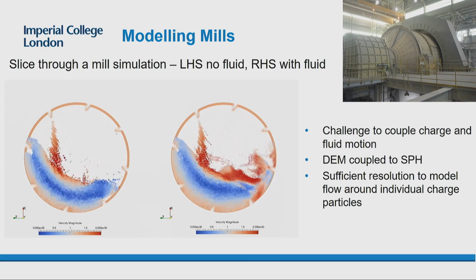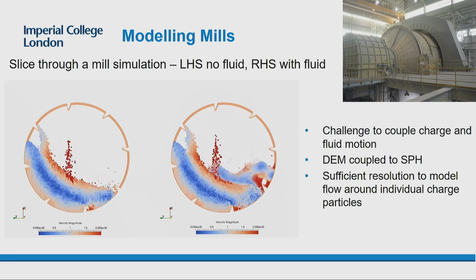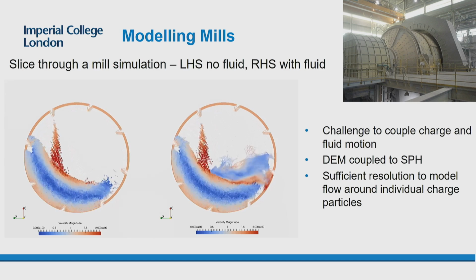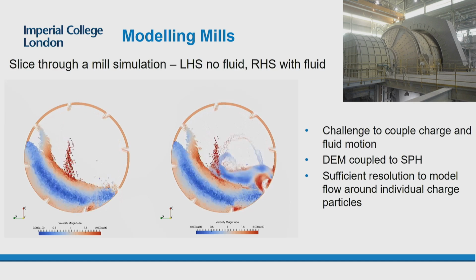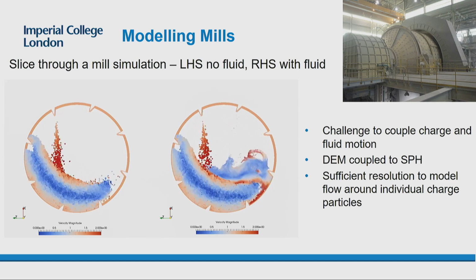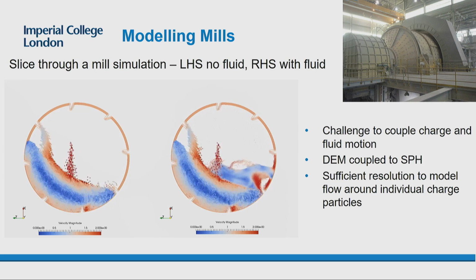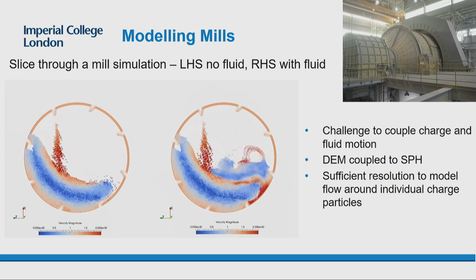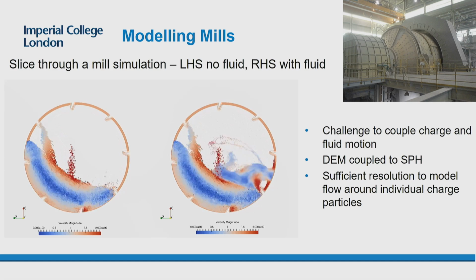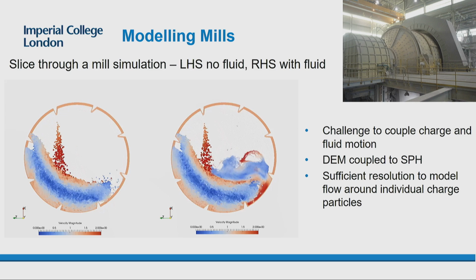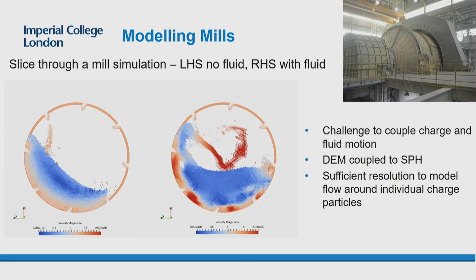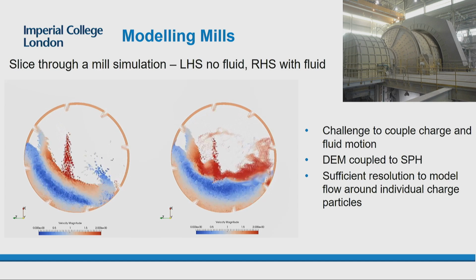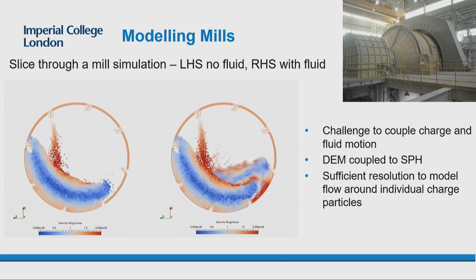So we've been doing a bit of work on the milling side, which is very much a new area. Again using that same SPH code, but this time coupled to another method called the discrete element method, we can start to simulate what's happening in mills. Here we have about 100,000 steel balls we're simulating, the things that are tumbling, on the left-hand side without any fluid, and on the right-hand side with fluid. The left-hand side is the sort of simulation routinely done by lots of different groups. The big challenge is trying to do it with the fluid. The one on the left-hand side took my code about half a day to do. The one on the right-hand side was about 2 weeks. So there's a really big difference between doing it with the fluid and without the fluid.